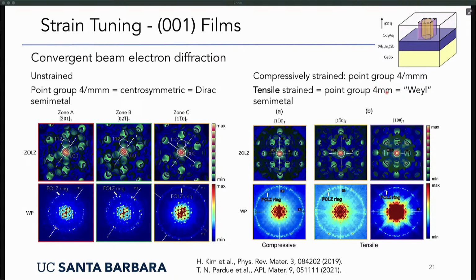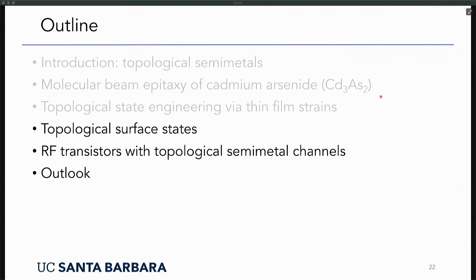And in terms of the atomic structure, it means there are very, very subtle arrangements of the relaxations around the cadmium vacancies. That's the difference between these two structures, and they look energetically very close. And so a small tensile strain causes this inversion symmetry broken structure to be the preferred one. So that's as far as thicker films are concerned.